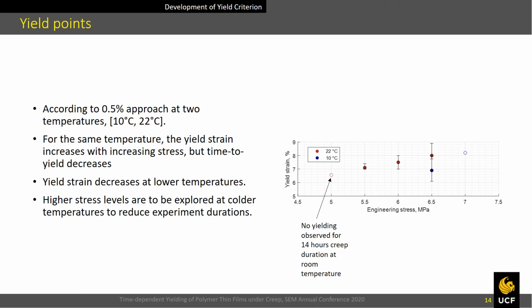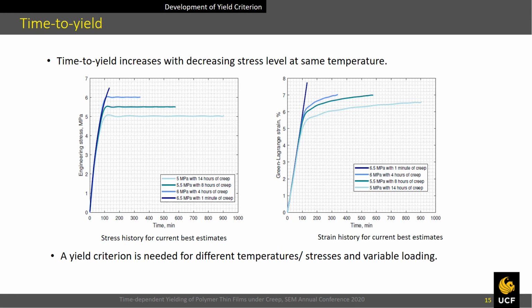Investigation of the initial data displays an increasing trend of the yield strain with increasing stress level. Also, yield strain decreases at lower temperatures. The time to yield increases with decreasing stress level at the same temperature.